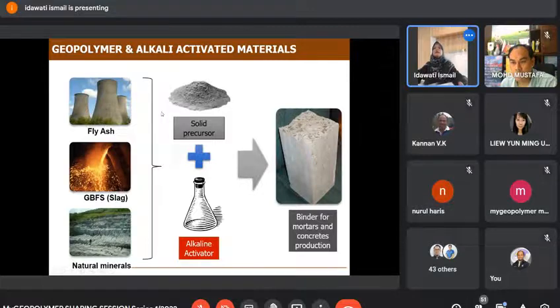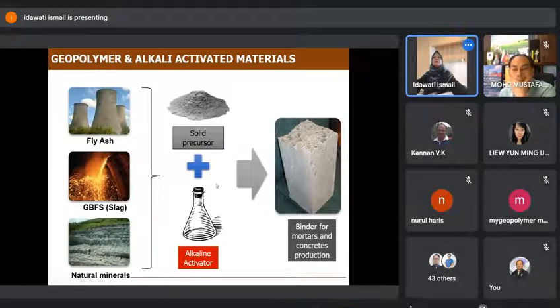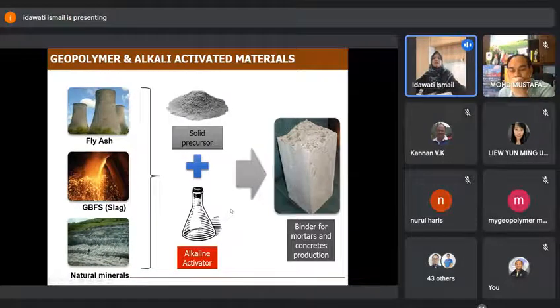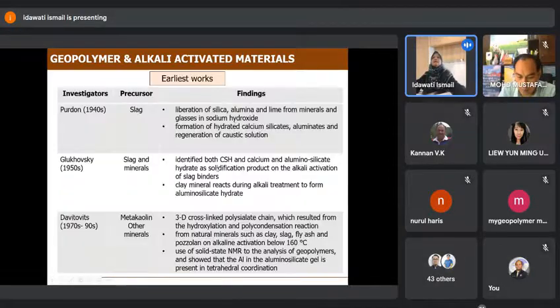So we call that the first starting material, which is the solid precursor, and we mix it with some alkaline solution. We found that when we mix them, there are some reactions, and they become hardened and can be used for production of mortars and concrete. So when did this start? Actually, the use of geopolymer or AAM started way back.